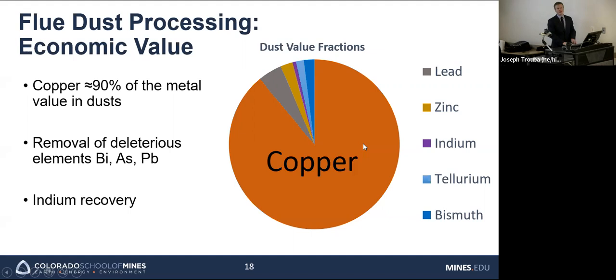By now, it should be apparent that when they process the dust, the main goal is going to be to maximize recovery of value. So dust processing needs to focus on copper recovery. Second, the copper needs to be separated from deleterious elements. I've mentioned bismuth in particular, but arsenic and lead can cause issues in copper processing, and their removal is also beneficial. Then, hopefully, the developed method also provides a potentially even further enriched stream of indium for recovery.